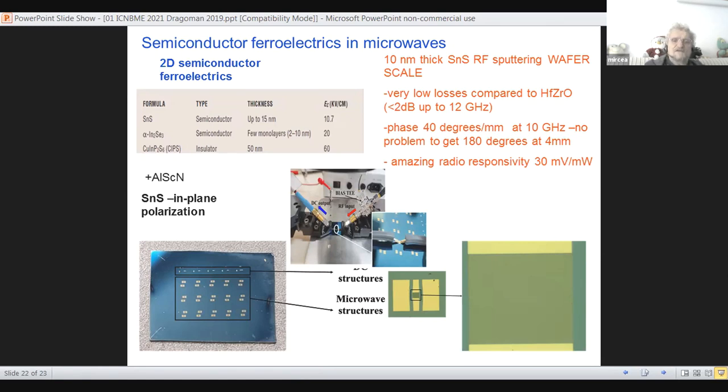We have developed all of this in the last 3 years after we learned from materials people that hafnium oxide could be ferroelectric. It's difficult to grow. It is grown by atomic layer deposition, which is a complicated instrument. Many people don't have such equipment. We have this in IMT. In this way, we have succeeded, learning from others, to obtain ferroelectricity in a thin film which is 6 nanometers thick, and even 4 nanometers thick.